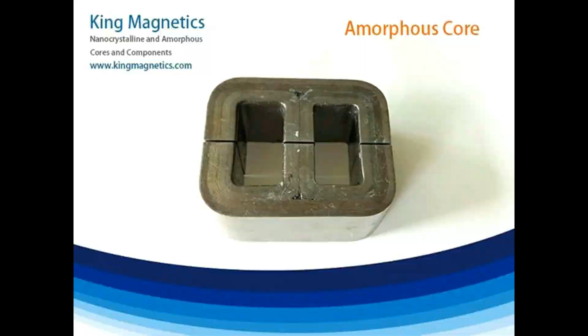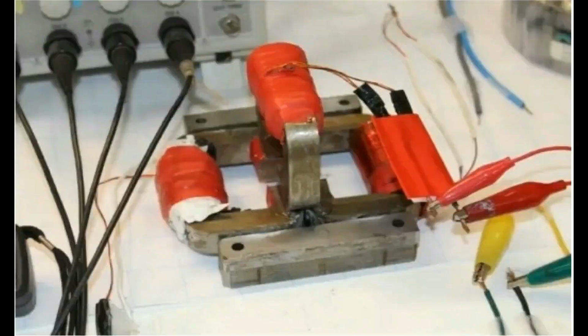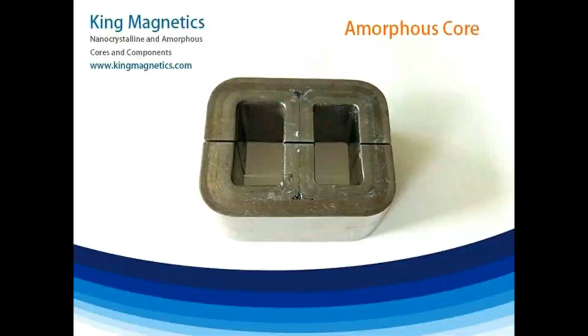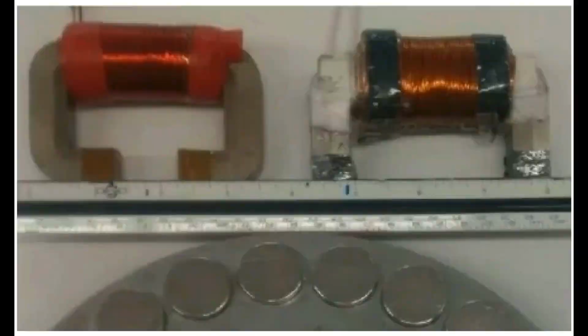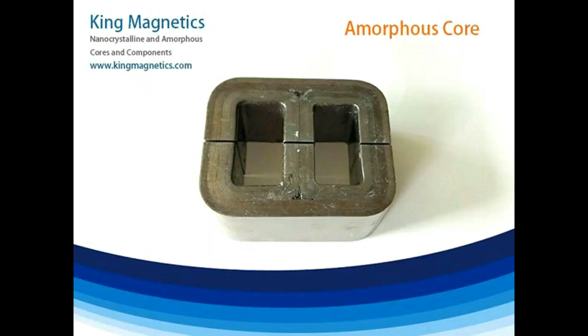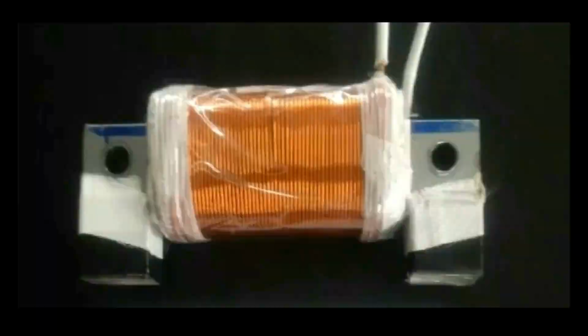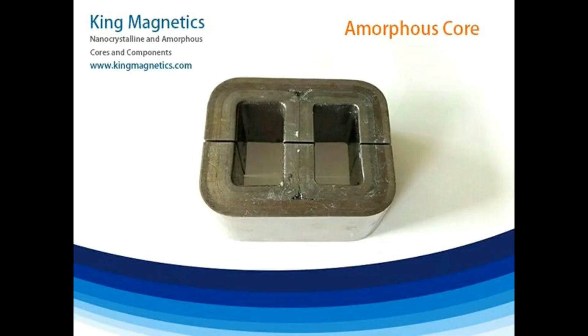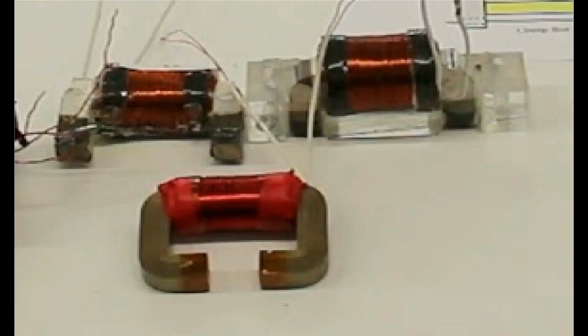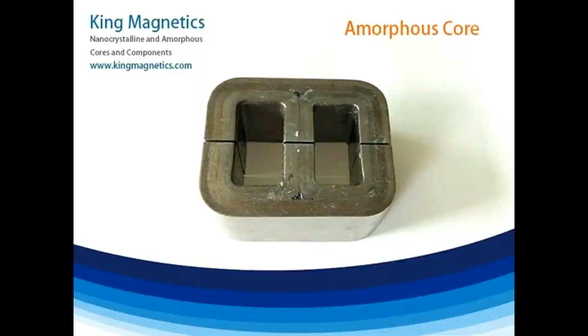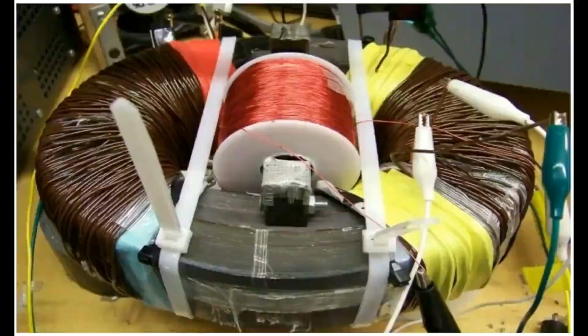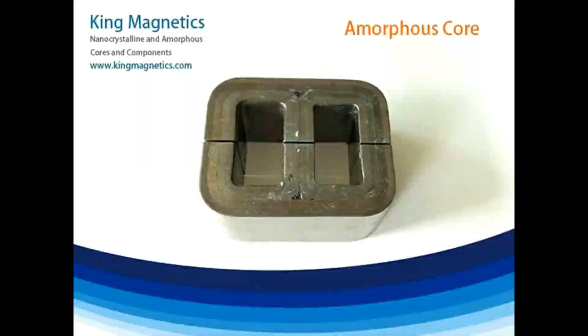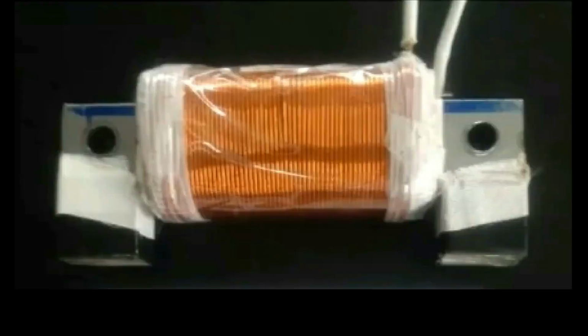On the downside, amorphous alloys have a lower saturation induction and often a higher magnetostriction compared to conventional crystalline iron silicon electrical steel. The main application of AMTs is grid distribution transformers rated at about 50 to 1,000 kVA. These transformers typically run 24 hours a day and at a low load factor, average load divided by nominal load. The no-load loss of these transformers makes up a significant part of the loss of the whole distribution net. Amorphous iron is also used in specialized electric motors that operate at high frequencies of perhaps 350 Hz or more.